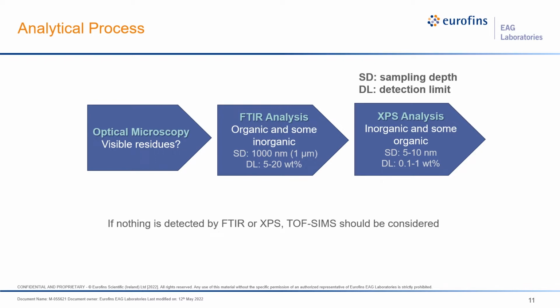So this is not a particularly sensitive technique, which is why we also do XPS analysis. XPS will tell us a little more inorganic information, although it will tell us some organic too. So these two are very complementary. Here, we're sampling from a very different volume. This is a much more surface sensitive technique, so we're looking at the first 5 to 10 nanometers rather than 700 to 1,000 nanometers. The other thing is this is much more sensitive, with much better detection limits than anything else. If we don't detect anything under these conditions, we also have a different technique called TOF SIMS, which we'll discuss a little later. It's extremely sensitive, so it's useful if you're looking for very minute contamination. But between these two, we should get a good idea of how clean these ovens are. Are they outgassing, and do they have remnants of previous samples that might be contaminating?